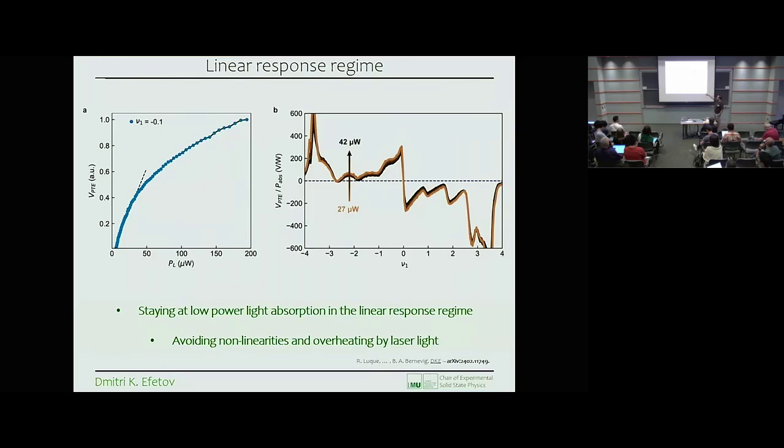And so here is the Seebeck measurement, the photovoltage as a function of laser power. We're really trying to stay at a few microwatts. Also, what we checked is that by changing the laser power, the curves don't change, right? If we would heat them very much up, we would be able to tell, because they would start looking like high temperature measurements. So the temperatures are lower than that at which any gap opens up.